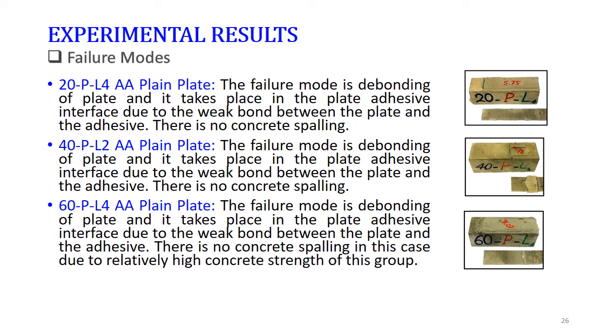Okay, there are different failure modes, but for most of the elements, which we call plain plates, without any treatment of the surface, the failure is very much by debonding. With the exception of a few of them, especially those which have high strength concrete, they show not debonding but a little bit of delamination, but not much. So debonding is the most dominant failure, which is telling me that the aluminum surface as is not very good in providing high bond stress or shear stress between the aluminum and the element that you need to strengthen. So something needs to be done about the surface.